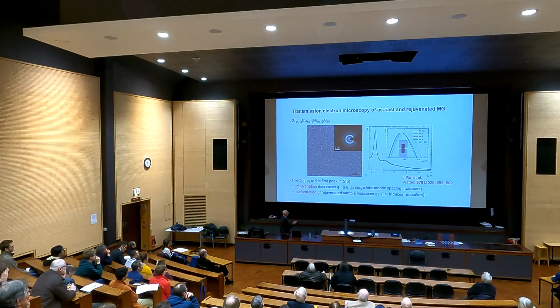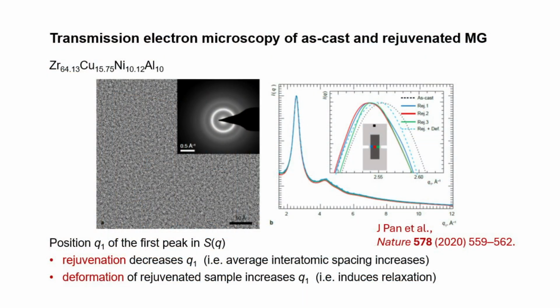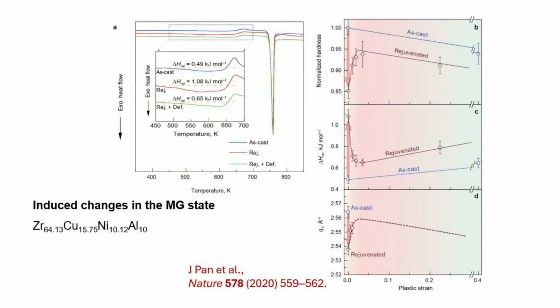We can look at the diffraction pattern, and that evolves to tell us that the material has become less dense, although it was compressed. This is stored energy. So what happens with these pink arrows is the effect of our processing in that notch cylinder. We drive the hardness down, we drive the energy up, and we drive the material to lower density. And then, that's our starting material.